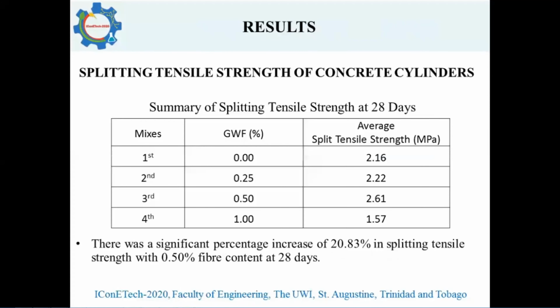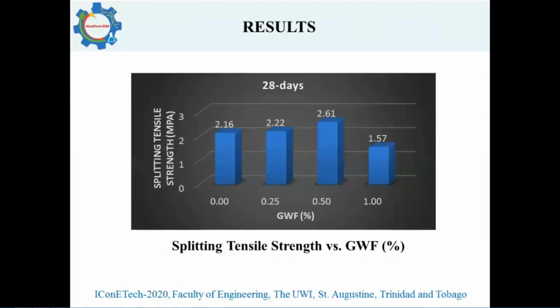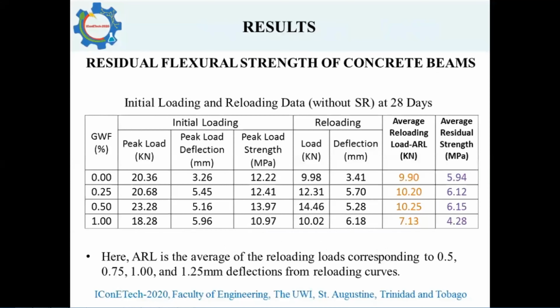Splitting tensile strength of cylinders. Also from the bar chart, there was a significant percentage increase of 20.83% in splitting tensile strength with 0.5% fiber content at 28 days. Then flexural and residual strength of concrete beams.